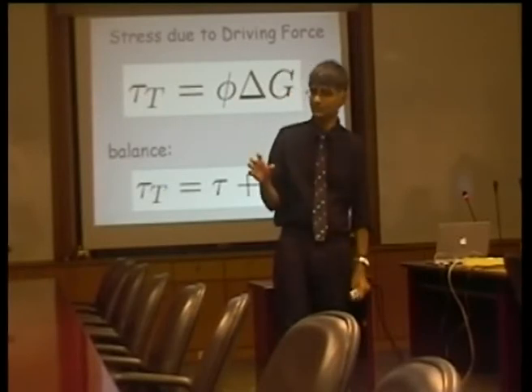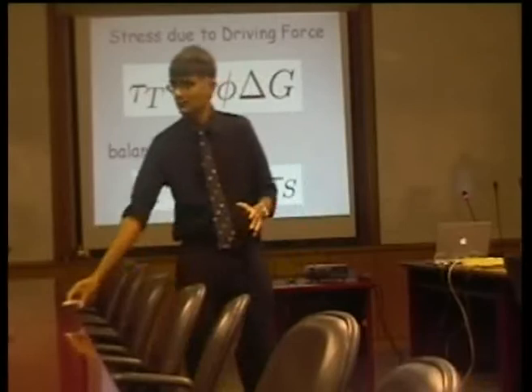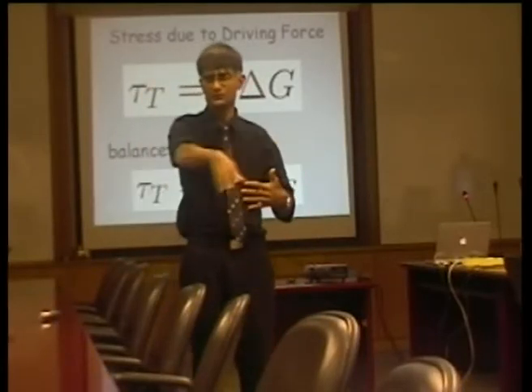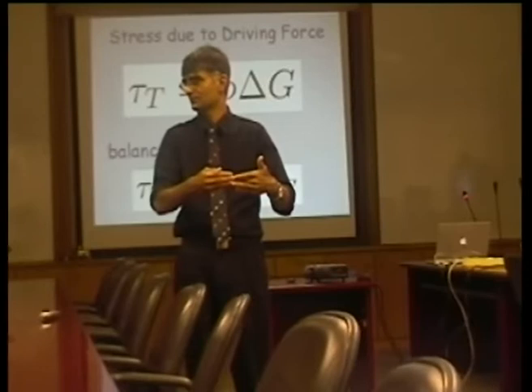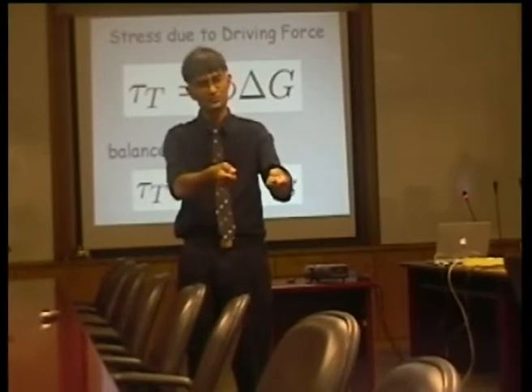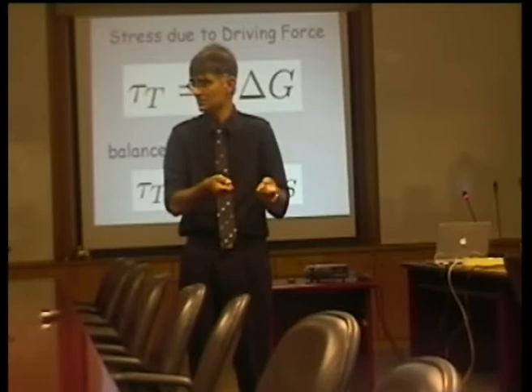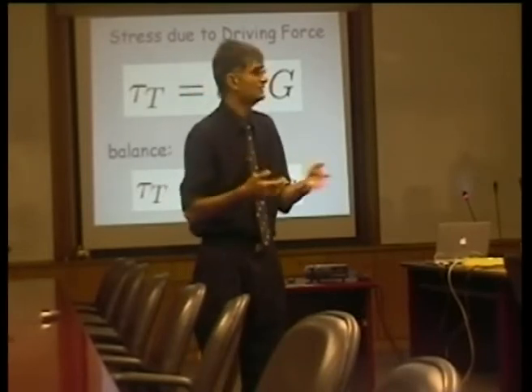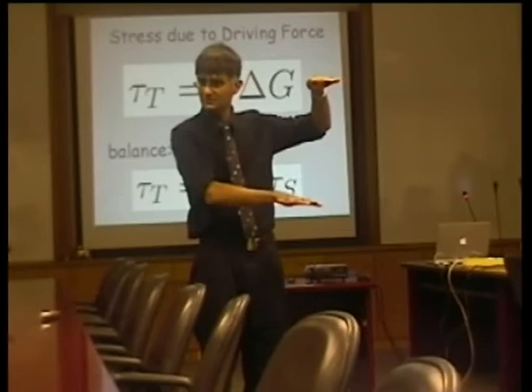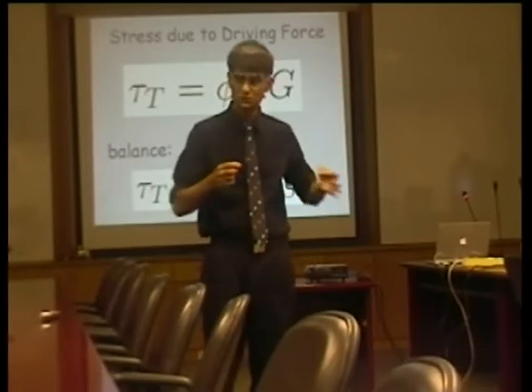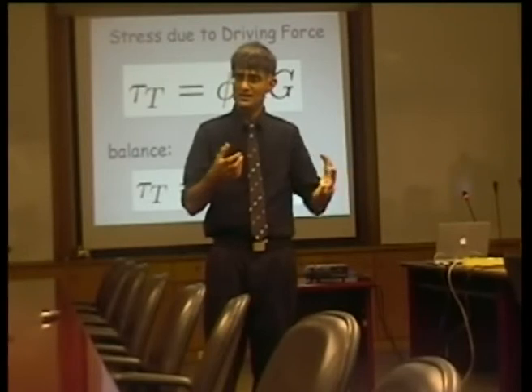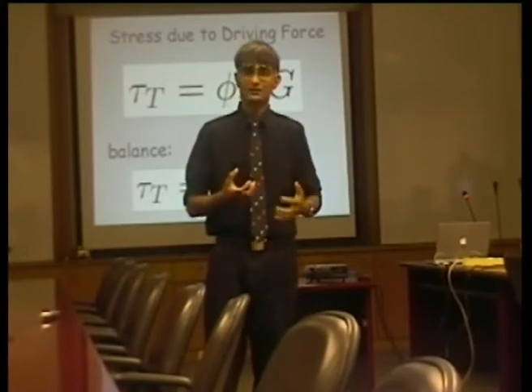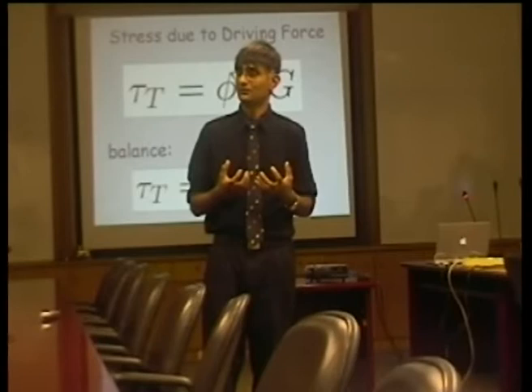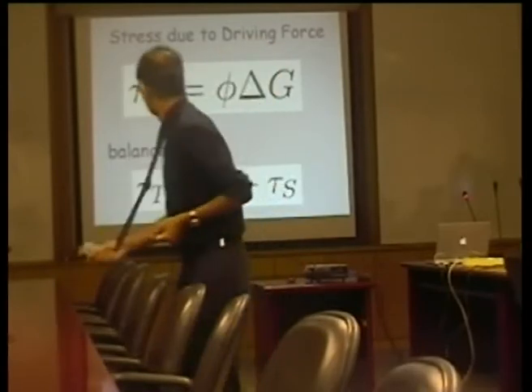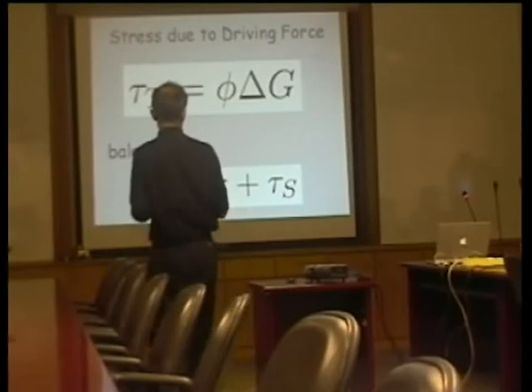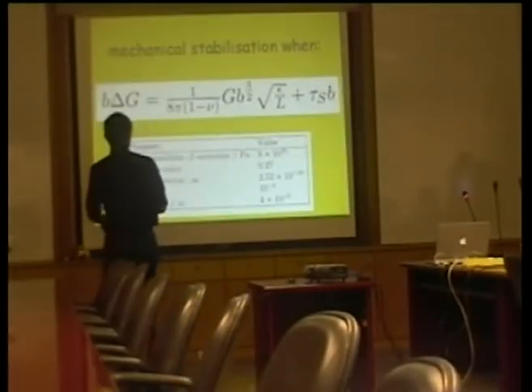Just don't worry about the detail. All we are doing is we have two stresses. One, we've got a jungle of dislocations, and we've got to get past that. So we are working out how much the dislocations resist the movement of the interface. And what is driving the interface is the difference between the energies of austenite and martensite. So we can work out the stress which pushes the transformation interface. So it's an incredibly simple theory, and it's very surprising that nobody has thought about this until now. All we have to do is balance those two stresses